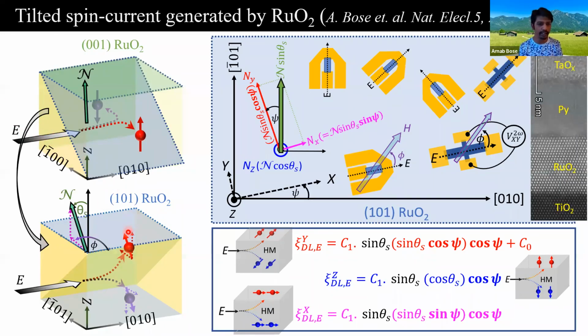Rather, we are measuring spin current in this direction that has an angle. That's why the additional sin theta comes. So finally, the summary is: in the 101 oriented ruthenium dioxide permalloy bilayer, if we measure spin orbit torques, we should see a clear angular dependence of different types of spin torques.